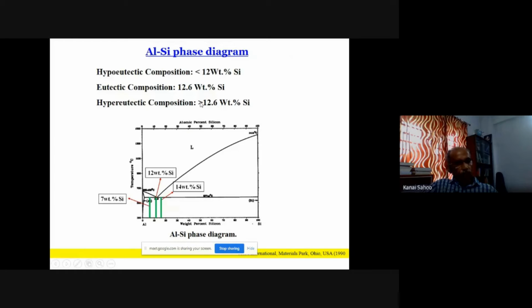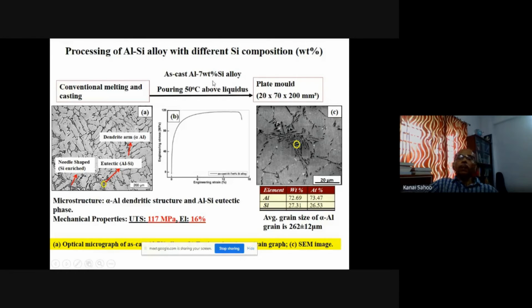Here I've shown you the phase diagram, because most students, when they do some project work or research, never follow the phase diagram. This is the first thing a researcher or student must use, the phase diagram. That's why I put this. So three compositions we have taken: 7%, 12%, 14%. Mainly I concentrated on the 7% silicon aluminum alloy. In the as-cast structure, you can see all interdendritic structure, a lot of elongated shapes. Due to these shapes, the strength is very low, 117. Please note this value, 117, with 16%. We'll see how this 117 goes to nearly 400. The average grain size is around 260 micron, plus or minus, with a highly elongated structure.